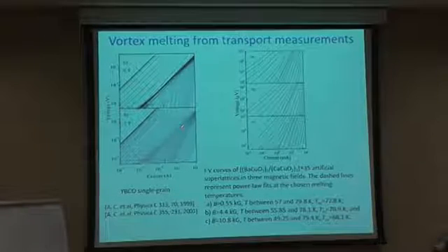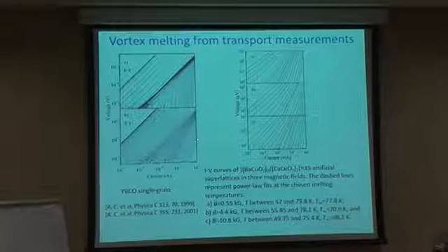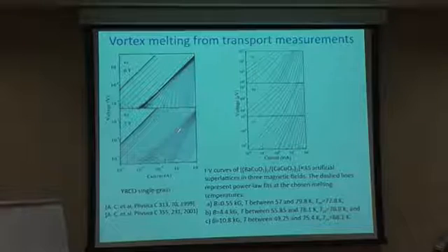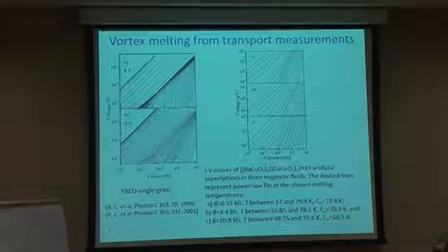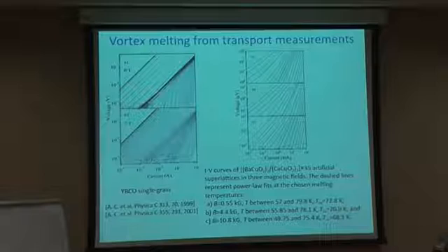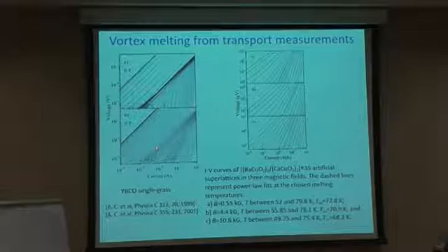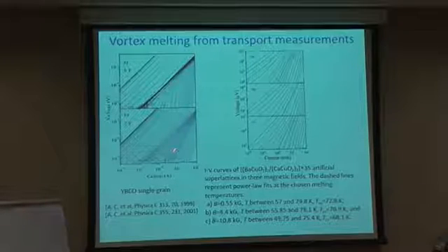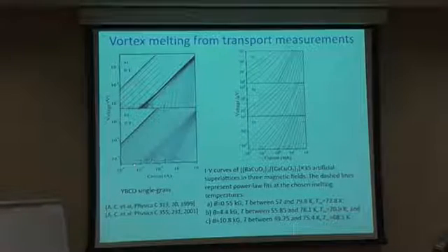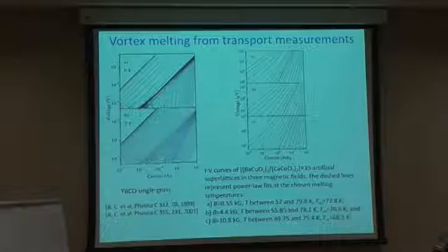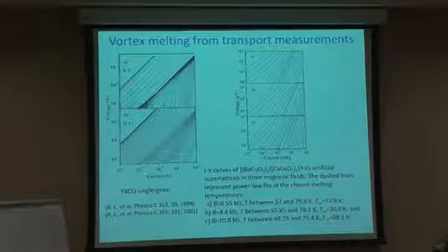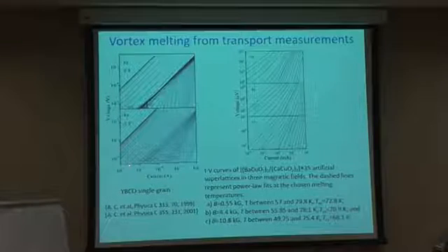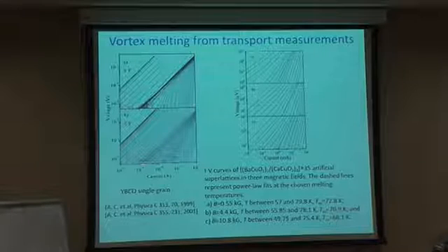Here it's again a linear slope, but now it's in the log-log plot, and that slope for a bidimensional system is the Kosterlitz-Thouless transition, and the slope will be 3. Here you see at lower temperatures, the curvature goes down. So here you see we have 10 to minus 9 volts. So we have used a very sensitive SQUID picovoltmeter to manage to obtain these values here.